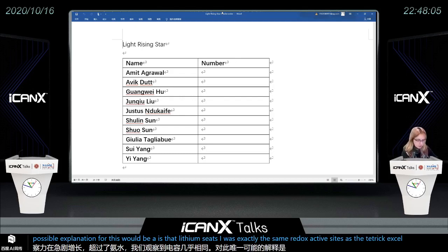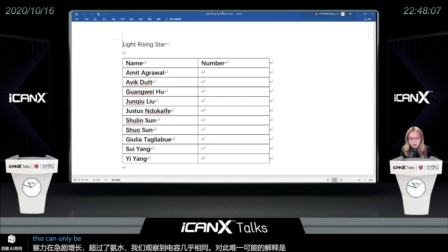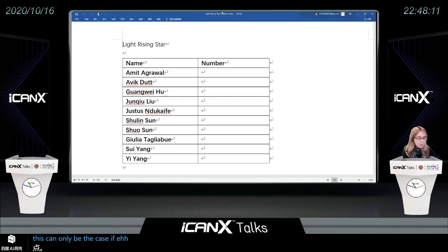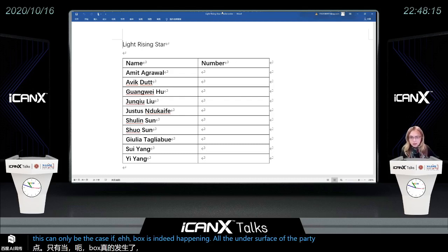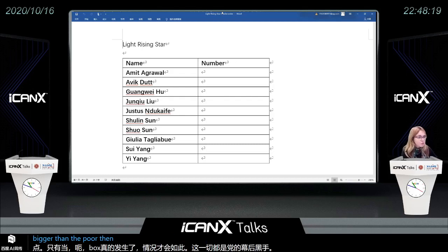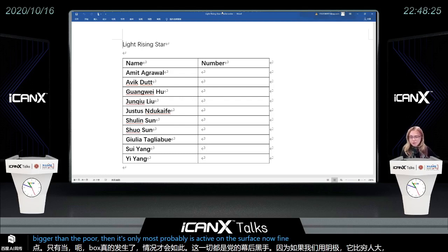And this can only be the case if the redox is indeed happening only on the surface of the particles. Because if we take the cation, which is bigger than the pore, then most probably it is only active on the surface. Now, finally, we wanted to again demonstrate the scalability for this system.